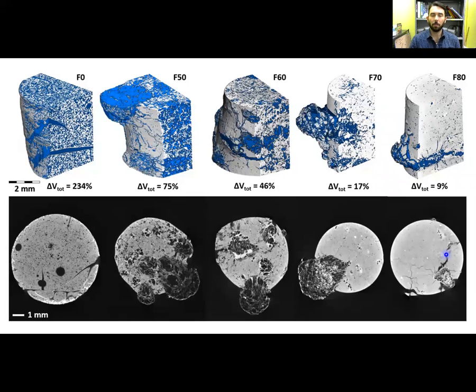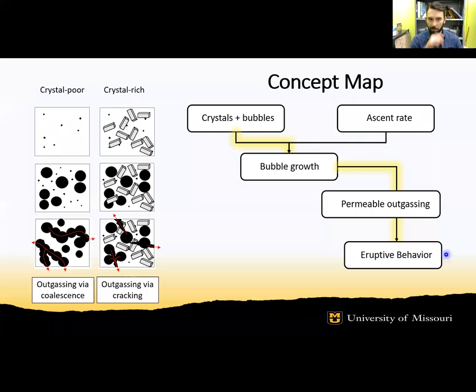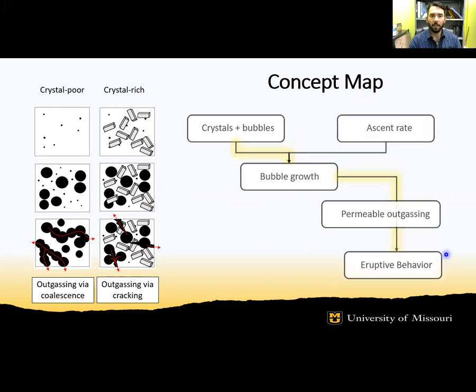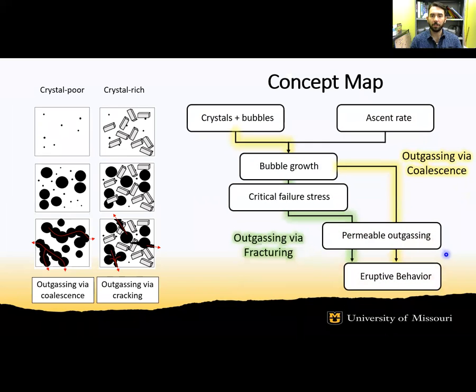This crystal framework, comprising 50% crystals, physically dampens bubble growth and impedes coalescence. At the same time, trapped bubbles increase the critical stress required for brittle failure. This prolongs outgassing. This demonstrates that permeability, in addition to bubble coalescence, can be achieved efficiently via pore pressure-induced cracking, and as such, we infer this to be the dominant outgassing mechanism in crystal-rich magmas.